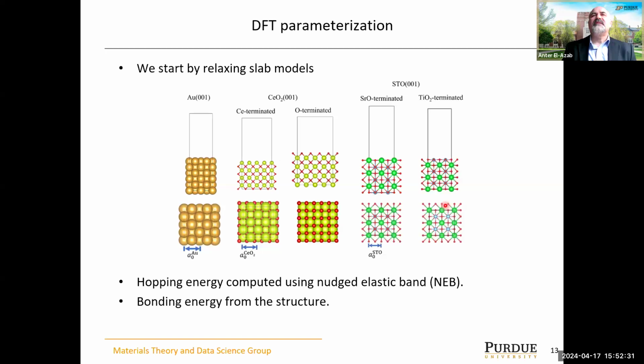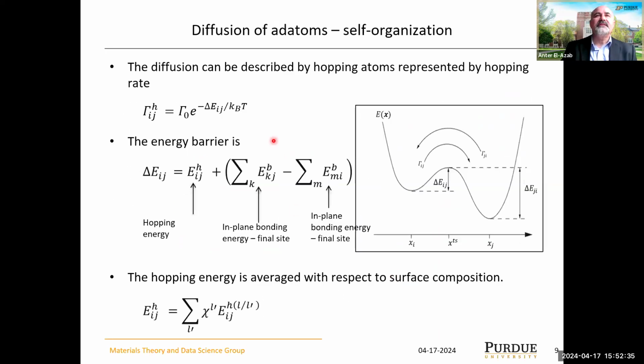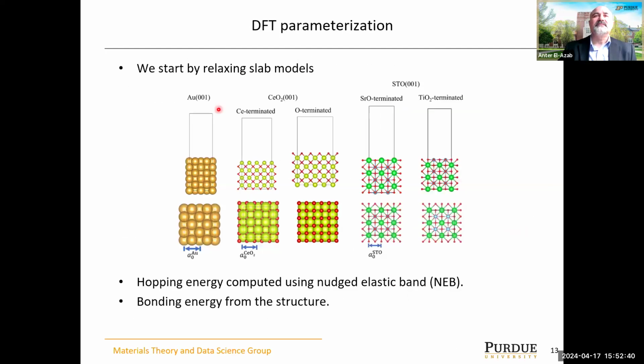So with this, we need to do the parameterization of these energies in the hopping rate using DFT. That's the work that Ahmed and a collaborator have done for the gold-ceria on STO system. We look at these things by the species that is deposited. We're depositing gold and ceria, and we consider ceria molecules in this particular case. In the beginning, these things land on the STO surface because you don't have anything deposited yet. But later on, when you cover the STO with your phases, now ceria or ceria and gold, the Au can land on gold or on ceria. The ceria molecules can also land on gold or ceria. So we have these 4 situations to look at hopping energies and also binding energies among them.